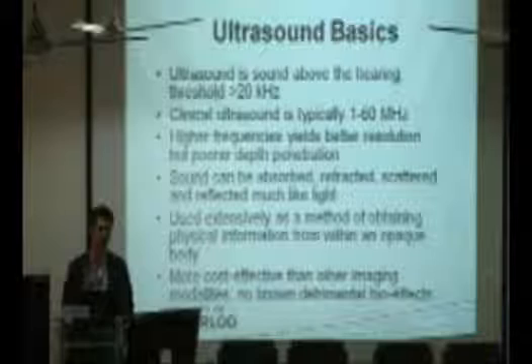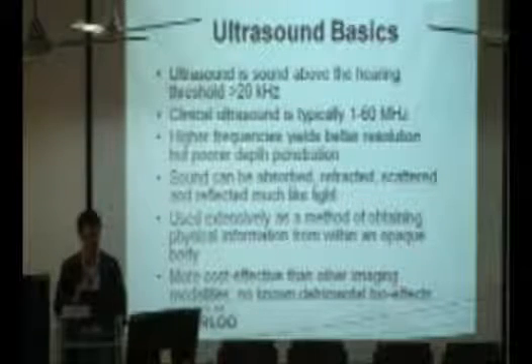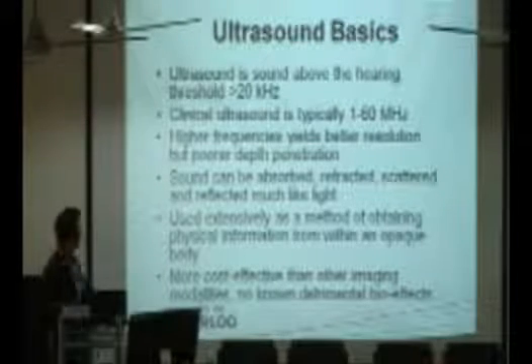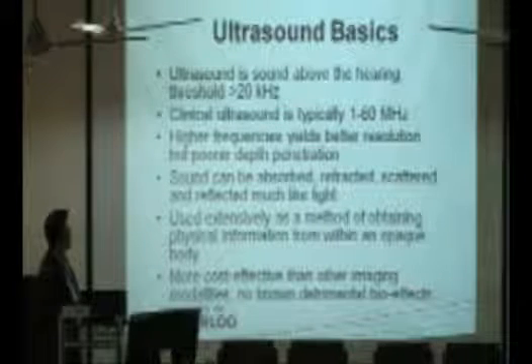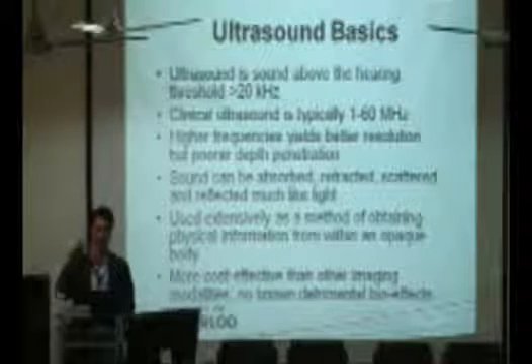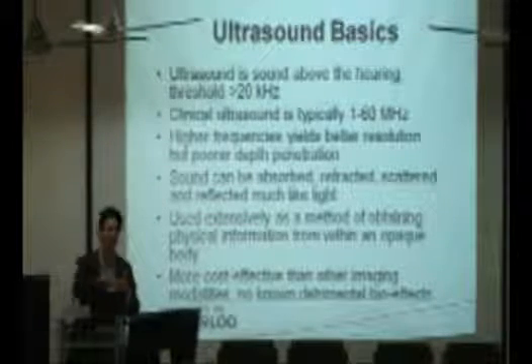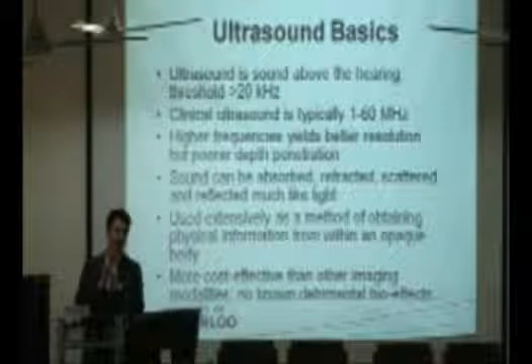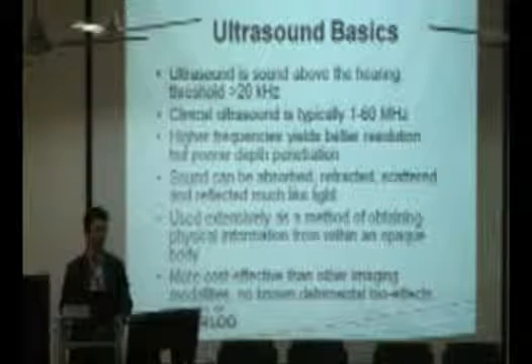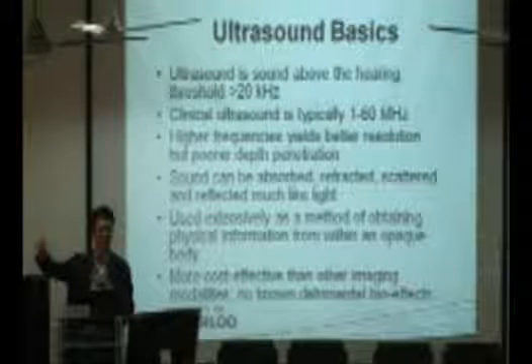So I know everyone knows what ultrasound is. I believe most people have done ultrasound imaging before. Now, I'm not going to talk about the basic definition of ultrasound, but I would say this. Clinical ultrasound is typically around 1 to 60 megahertz. For ultrasound, the higher the frequency, the less the penetration depth. The lower the frequency, the deeper the penetration depth. But high frequency gives us higher resolution. If we want to image really small structures within tissues, we need to move to higher frequency, although we are compromising on the penetration depth.